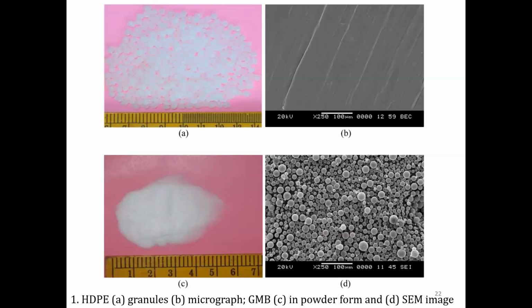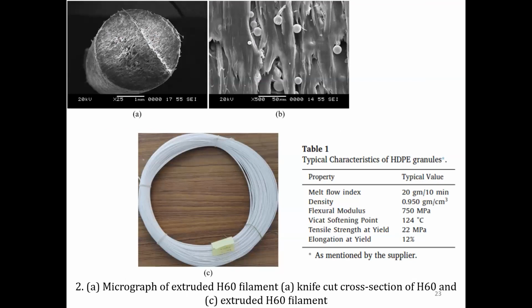What you see in figure 1D is a scanning electron micrograph of glass microballoons, wherein you can see a spherical particle without any surface defects. You have seen the cenospheres in the earlier slide, and such defectless features of glass microballoons ultimately result in uniform resin spread around them, aiding effective load transfer, because that's what we want for strength enhancement. And these glass microballoons with varying volume fractions are blended with the HDPE matrix. You can blend it with any. So this is how it looks.